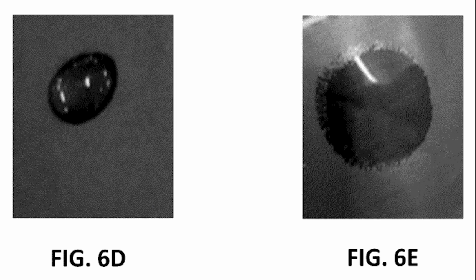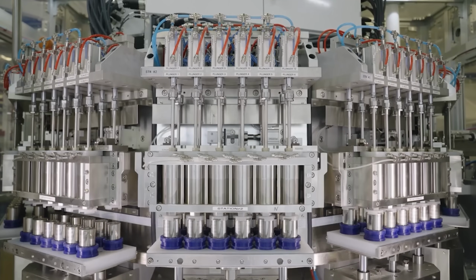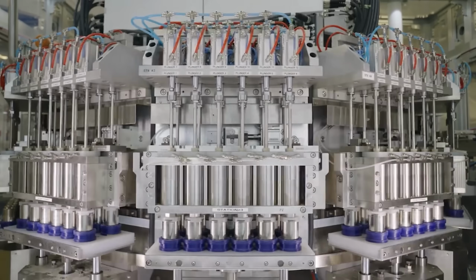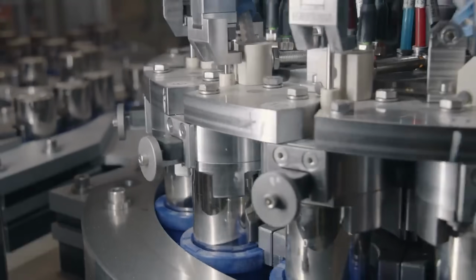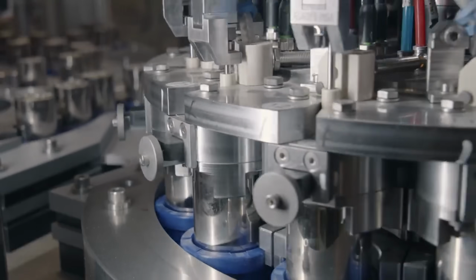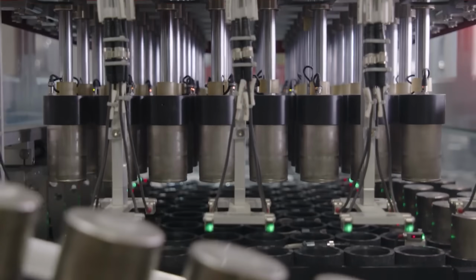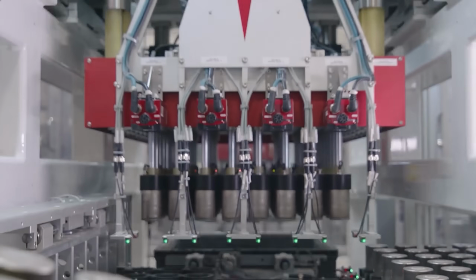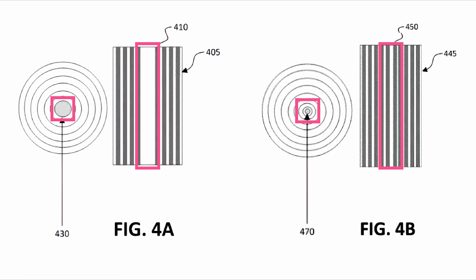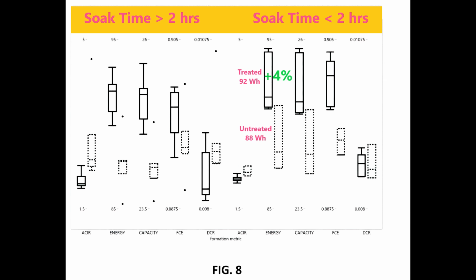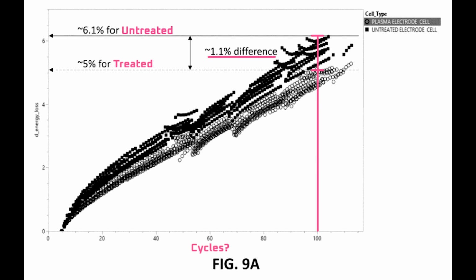Plasma treatment improves electrode wetting to such a great degree that it may allow them to skip process steps like vacuum filling, high-pressure electrolyte injection, and soaking, which would reduce the size of the manufacturing line and cell costs. The plasma treatment process also holds potential benefits for performance by decreasing the core size of the battery cell to increase energy density, reducing energy losses during formation, and improving longevity.